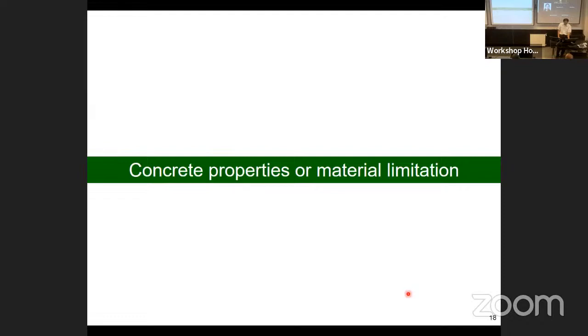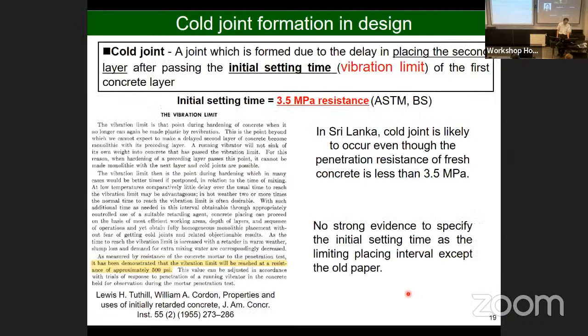Another issue in concrete property and material limitation in Asian countries: I often heard they suffer from cold joints. According to them, they follow this initial setting time, which is 3.5 MPa penetration resistance, according to ASTM and BS. But a Sri Lankan professor asked me, what is the background of this value? Then I checked many literature, and I only found a paper published in 1955. They just say this vibration limit will be reached at a resistance of approximately 500 psi, which corresponds to 3.5 MPa. But the background of the experiment is not clear, and they just follow it. And 3.5 MPa is very, very stiff. If so, cold joints easily occur.